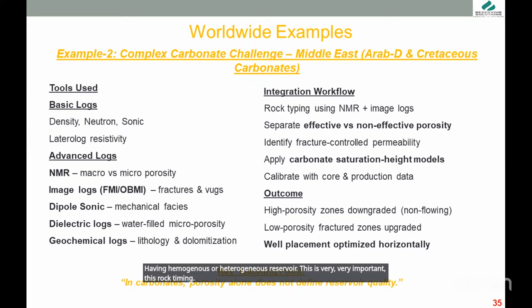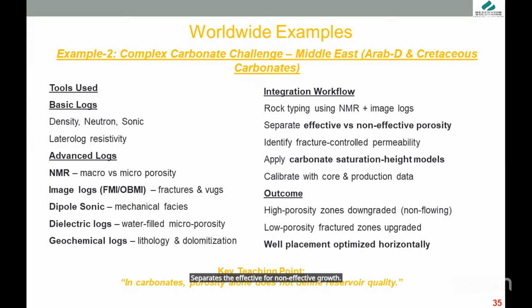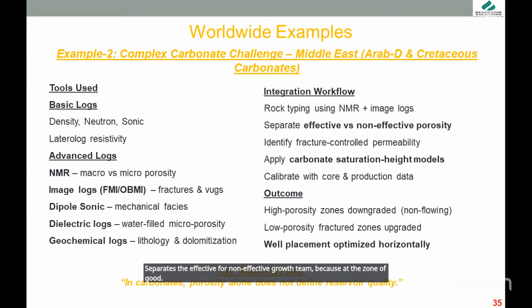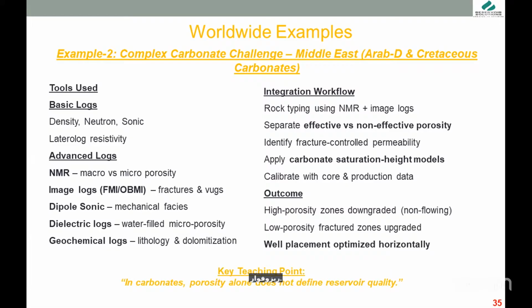Separate the effective from non-effective porosity. Because in a zone of good reservoir with good porosity, I will exclude the non-effective porosity in this reservoir zone. I exclude this from my estimation for the production, identifying fractures controlling permeability, and apply a carbonate saturation height model, calibrated with the core data and the production data.